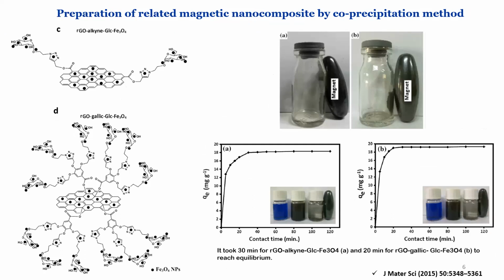Let me tell you about the stability of the dispersion of the hybrids without the magnetic nanoparticles. Because of having so many OH groups, the first three were stable in water for 2 weeks, and this bottom hybrid was stable for 3 weeks since it had more OH groups. Methylene blue as a cationic dye was selected. Adsorption reactions were carried out, and again, it took about 30 minutes for these hybrids to reach the equilibrium.